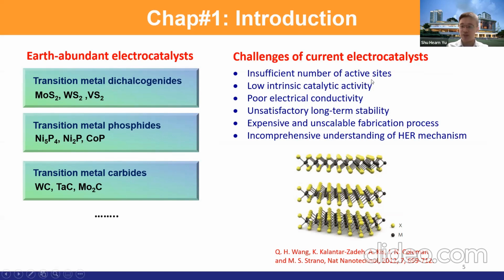So in the slide, we see that for MoS2, the edges are the active sites and the basal plane is not the active site. So we need to do something to increase the active sites. And it has low intrinsic catalytic activity. We can do chemical doping. We can do a lot of things to increase the intrinsic catalytic activities.